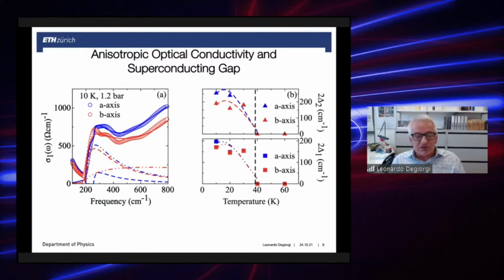Now you may ask, but where does this anisotropy come from? From the Raman spectra, we know that this is a multigap material. There are at least two superconducting gaps. And in fact, we did apply this Mattis-Bardeen approach within a two-gap scenario at each temperature. So you can extract the temperature dependence basically of the order parameter of this superconducting phase transition. And you see that upon crossing TC, there's indeed a stress-induced anisotropy at the lowest temperature in the relevant energy scale of the superconducting state.